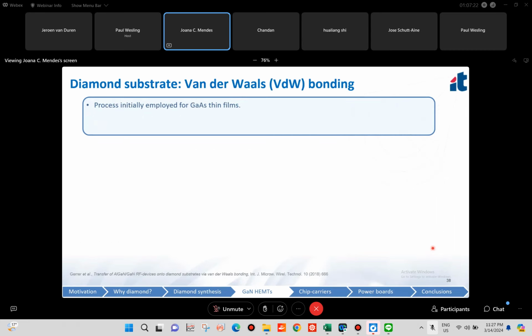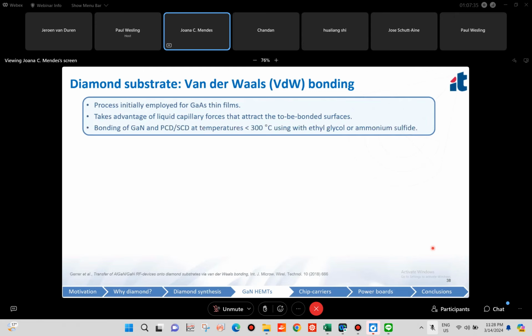And finally, the last process that we can use is the van der Waals bonding that was initially employed for gallium arsenide thin films. This process takes advantage of liquid capillary forces that attract the two surfaces, and it takes place at temperatures below 300 degrees C using a liquid like ethylene glycol or ammonium sulfide.